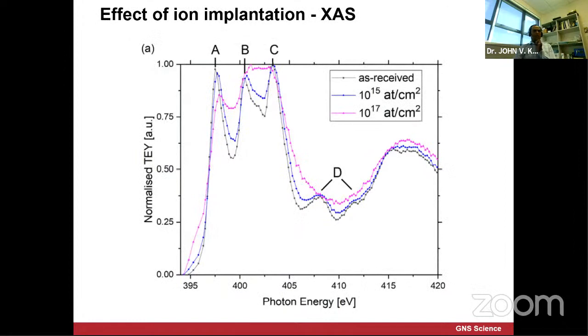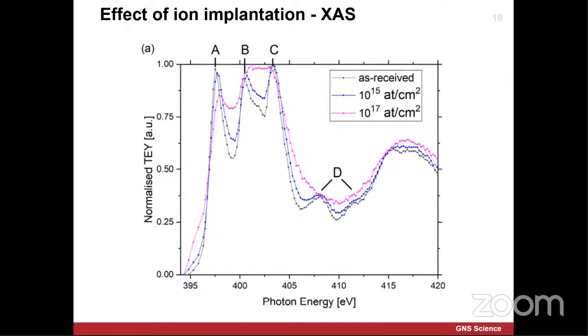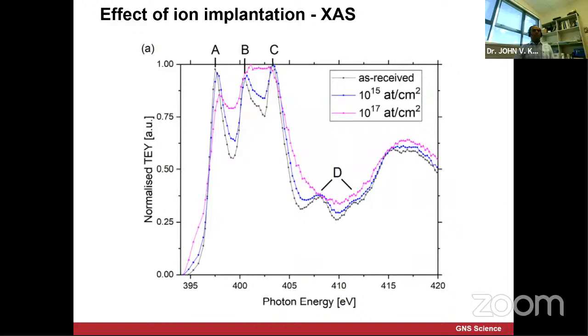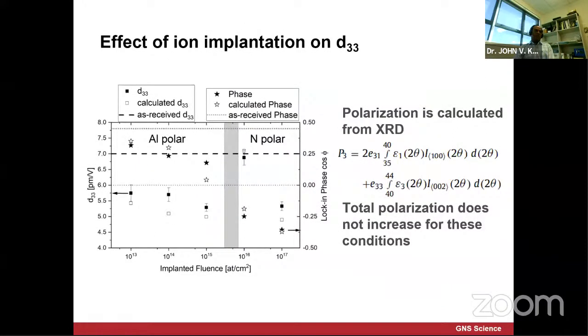But then we had a closer look based on synchrotron XAS data to get some insight into unoccupied metal states, which normally happens due to hybridization of nitrogen in valence states. You can see the reduced amplitude in the aluminum to nitrogen orbital along the C-axis, which is similar to the XRD larger spacing. Then you see shifts in B and C, which indicate replacement of aluminum with zirconium. So you're starting to see that there are polarity changes, which means you actually have induced strain in a particular plane, nitrogen to aluminum planar. This is a clear indication that ion beam engineering does change the induced stress and makes a shift in the lattices. So we dug deeper into this a bit more specifically.